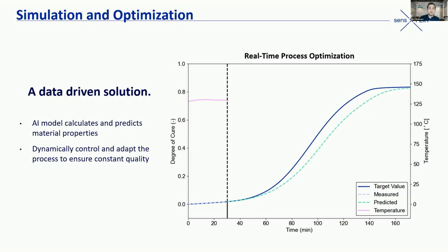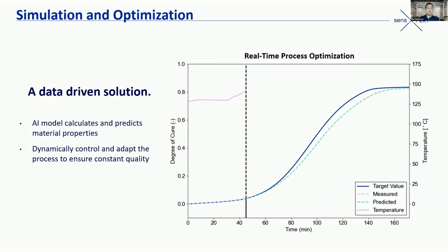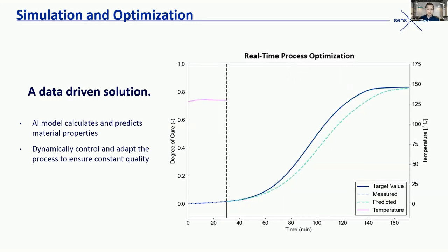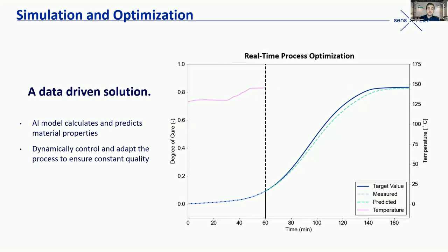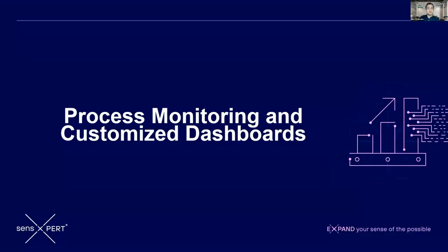And so we can see we're a little slow here in our degree of cure, but we can make that adjustment to the temperature. So as the temperature increases, the prediction updates, and we can make sure that every time, every cycle, we hit that same target. So it's just a really powerful tool. So not only can we measure the material properties live, we can make dynamic adjustments and see what's affecting the process, and just ensure that you have the proper guaranteed results.